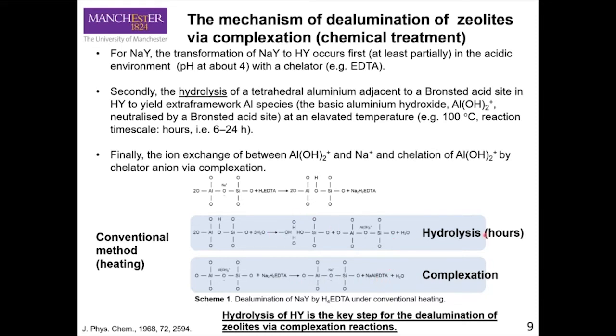So the first step of hydrolysis actually takes hours, making the whole treatment range around 6 to 24 hours at 100 degrees Celsius. And I thought about how we can improve this method. Since this one is the rate limiting step, is it possible for us to speed up this process? And then we found a paper, a research in other areas.